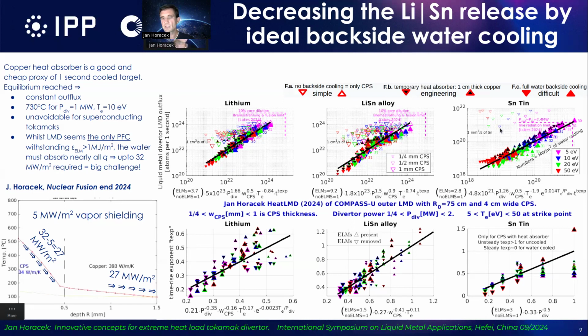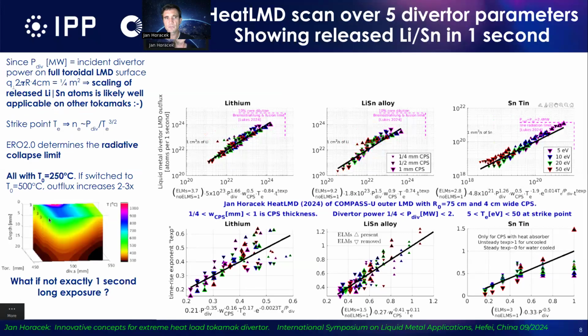In the case of tin, it's unfortunately not the case. You increase the amount of sputtered and evaporated particles of tin by 3 orders of magnitude, and you get above the limit very quickly, within a fraction of a second. So if there is cooling, full water backside cooling, these are the filled triangles, you see that the data are pretty similar to the case of just temporary cooling by just a piece of copper.